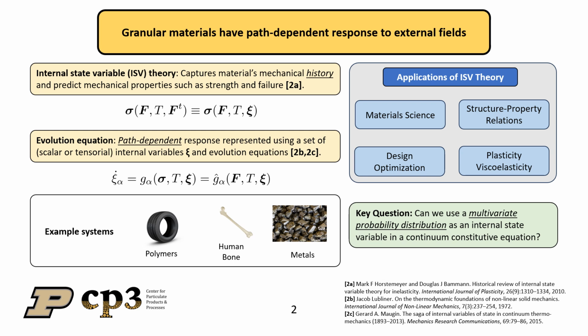Granular materials have path-dependent response to external fields due to the inherent heterogeneity of the contact force network and furthermore the resulting fabric of the microstructure. These heterogeneous materials exhibit irreversible deformations, and thus constitutive models need to incorporate temporal information. To model these materials, internal state variable theory provides a mathematical framework to incorporate features that contribute to the mechanical history of the material. One can then subsequently predict the resulting macroscopic mechanical properties such as strength and failure.